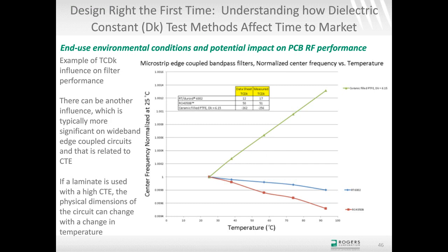There is another thing I want to throw out here. For tightly coupled, edge-coupled features, so a wide-band filter, let's say, when the copper features are very tightly coupled and very accurate, or at very high frequency where the dimensions are very critical, having a laminate with a higher CTE can be problematic. As the circuit heats up, it's very possible that these circuit dimensions will change due to the expansion and contraction of the laminate. And as that happens, the distance between these features could change. Now, to be honest, I don't see that very often. That's a little unusual, but occasionally, with very tightly coupled features, you can see a change like that.